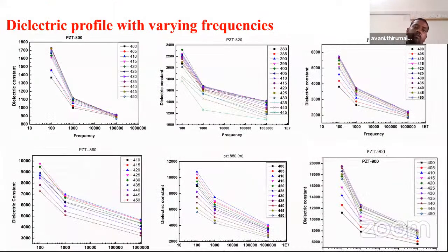This is the dielectric profile with variation of frequencies. At high frequencies, the dielectric constants of all the temperatures are almost close. At low frequencies, the dielectric constant varies because it varies easily, but at higher frequencies, the polarization varies with a little more difficulty. For that, this gives a clear picture of the dielectric constant versus frequency.